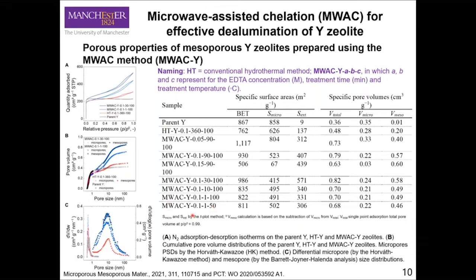So the key advantage of this method is that we intensify the process and reduce the time from the conventional 6 hours to 1 minute, and the temperature can also be reduced. Therefore, we anticipate there is some special interaction happening under the microwave condition between the framework aluminum and the chelating agent. I'm going to talk about the mechanism later. The whole method can be tuned beautifully, so we can play with the mesoporosity we would like to have in different materials by varying the treatment conditions.